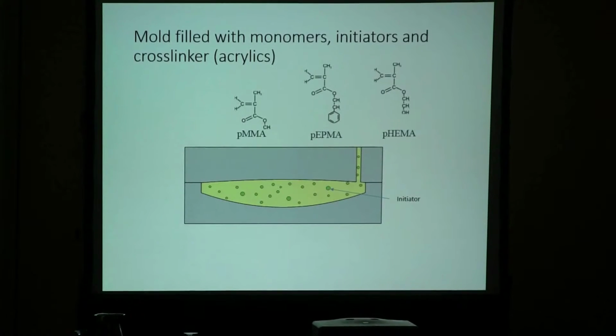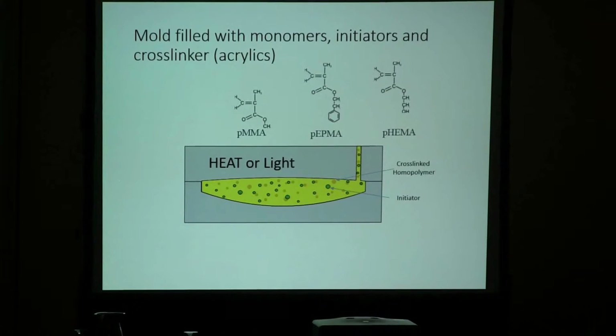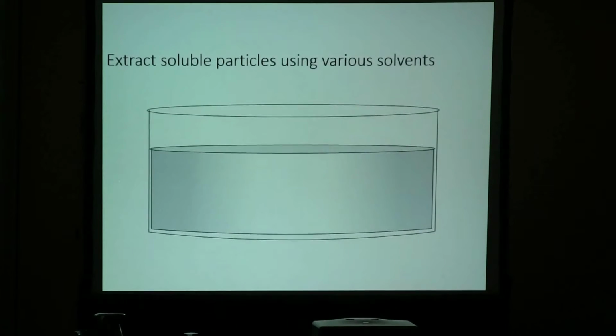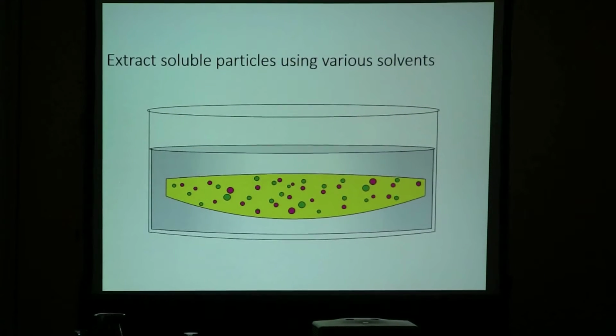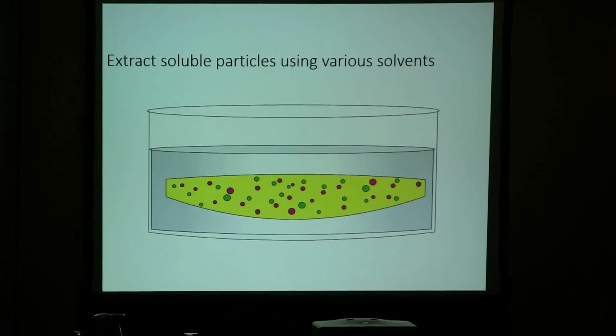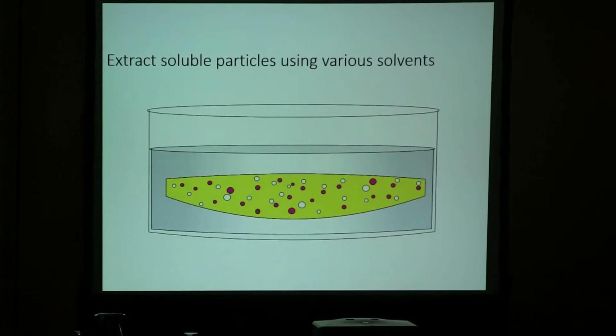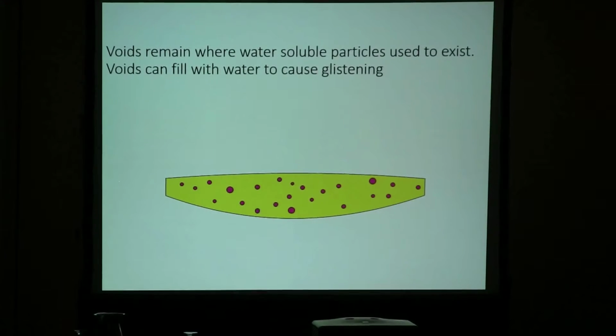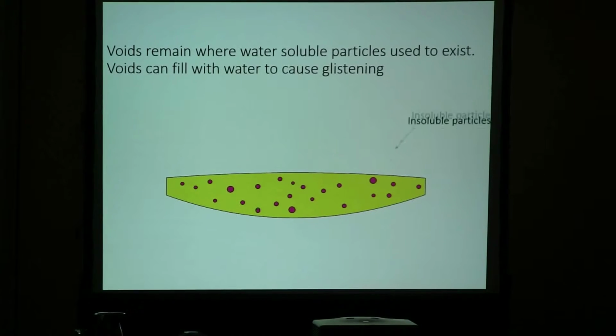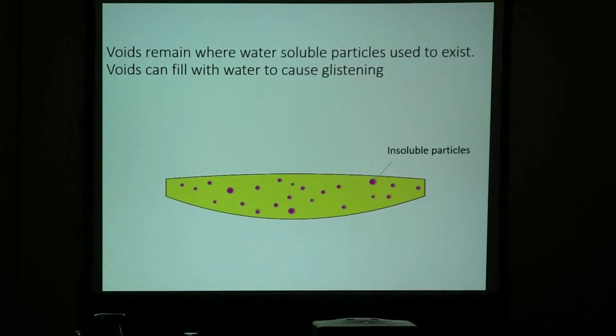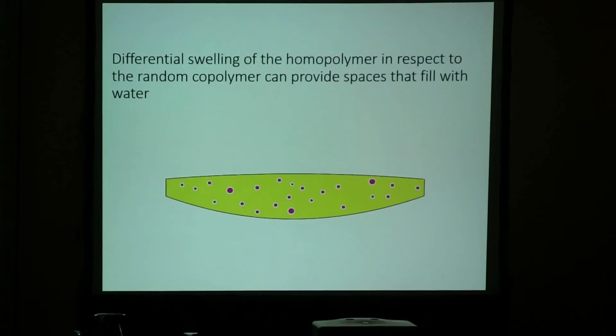The glistening in acrylics is due to the presence of initiator. When you polymerize it, you trap them in there. You also have inconsistencies of homopolymerization of some of the ingredients for acrylics. So if you were to extract lenses, which is often done with intraocular lenses, you can pull out the soluble particles, but you're left with voids that fill with water, which causes glistening and hazing. The insoluble ones stay there, but they swell differently, and this becomes the area where you also get water entrapment and glistening.